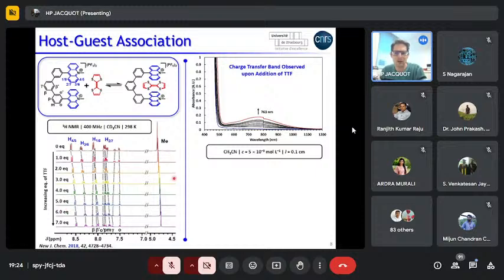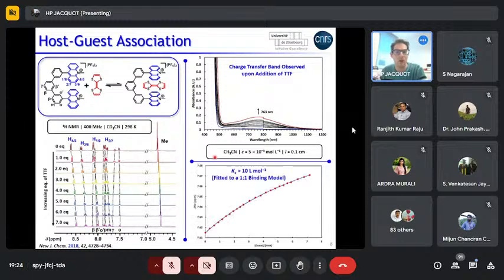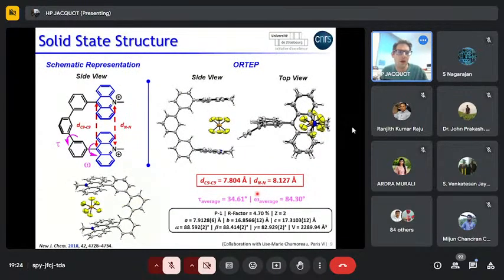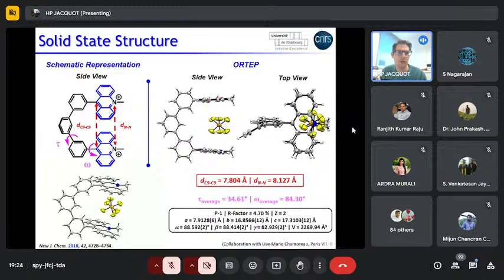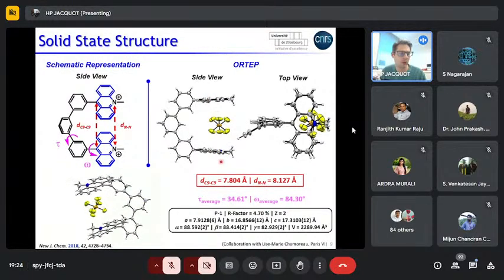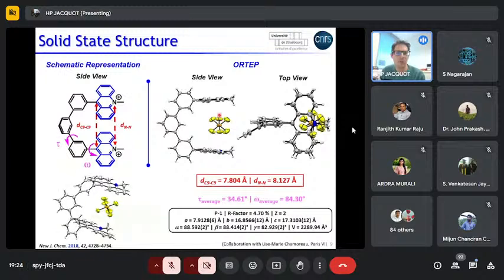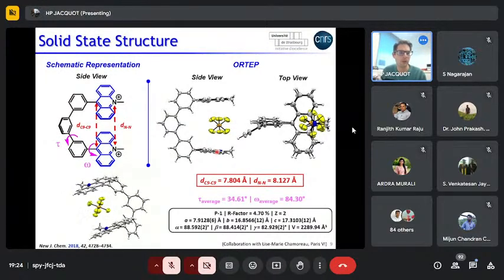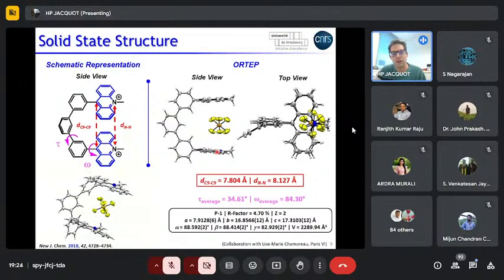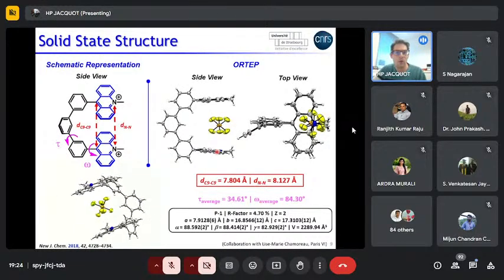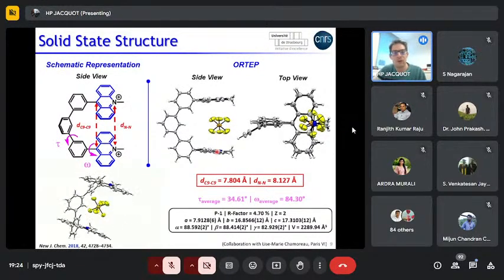And when I fitted this data to a mathematical model, actually a one-to-one binding model, I ended up with a very low binding constant of 10 molar minus 1. So basically it's ridiculous. It's like we have no interactions. Fortunately, we were able to grow crystals, and the molecule crystallizes in its U-shaped conformation with one PF6 in between the two acridiniums. So the acridinium distance is roughly 8 angstrom, which is actually too big to ensure pi-pi stacking interactions. And we tried to understand how we could optimize the design of the molecule.